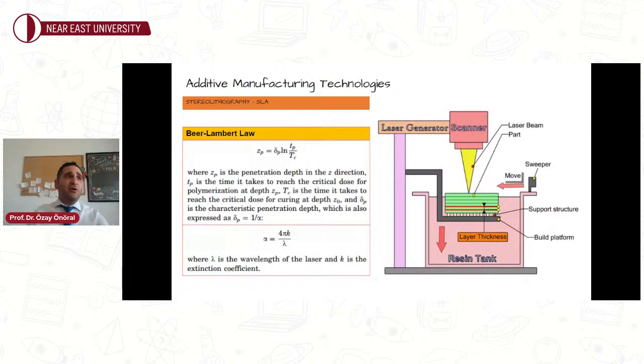Definitely, the accuracy of SLA fabricated products is very critical, and it depends significantly on the curing depth of the polymerization, which is described by the Beer-Lambert law, as you see in the slideshow. Moreover, the extinction coefficient K depends on the intrinsic properties of the resin, which includes the loading fillers, the surface of the fillers, and the refractive index of both fillers and the resin.